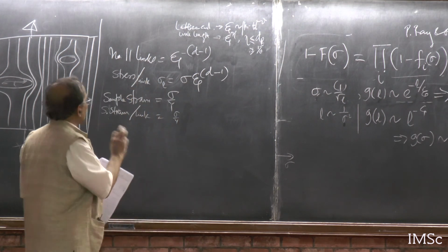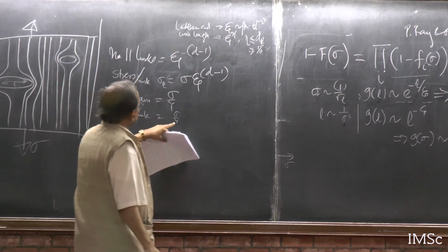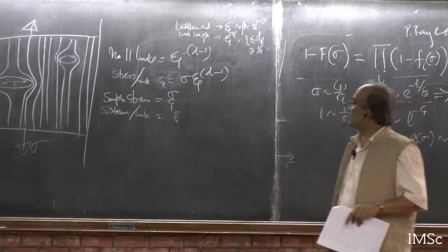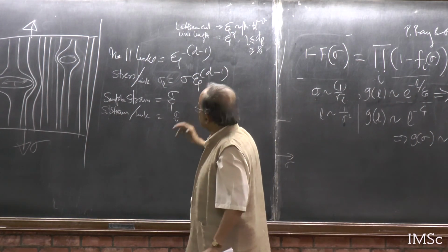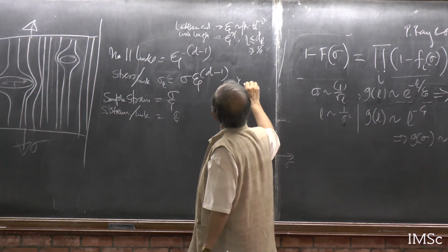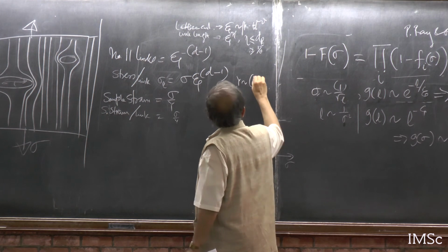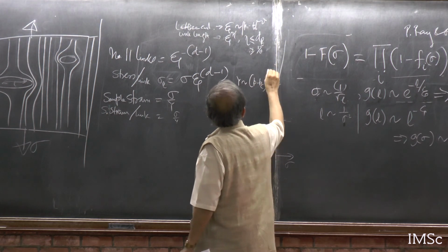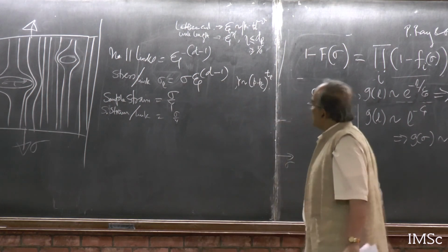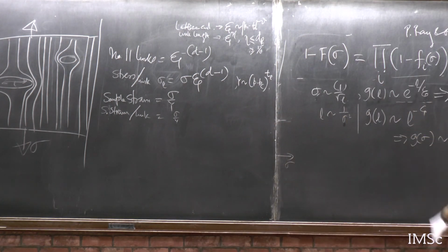So that is one estimate. For linear systems there are other ways of estimating. Sigma is sigma, but people know that Y, the modulus of elasticity, has been studied, and it goes as p minus pc to the power say t elastic. I don't want to go into that, as it can be found out from connections to the correlation length exponent and other things.